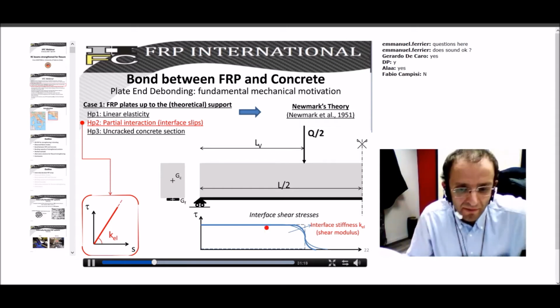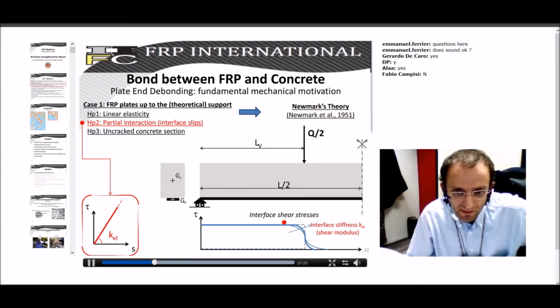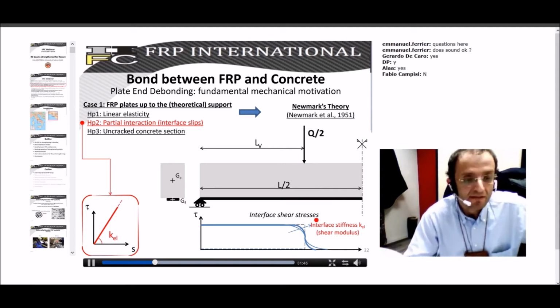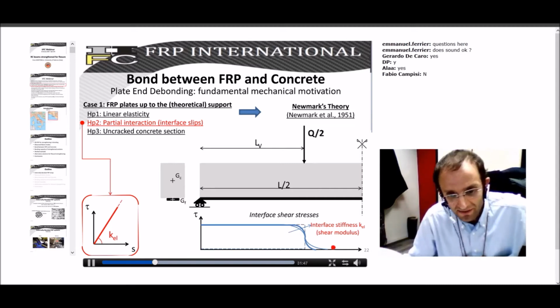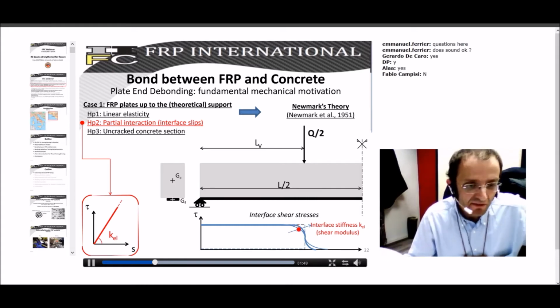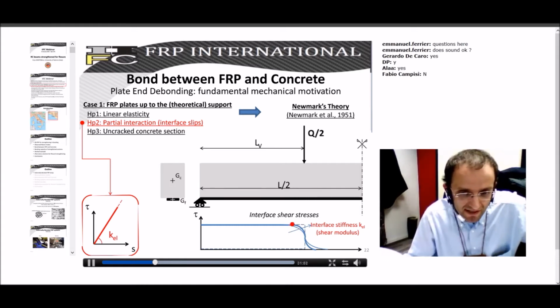But you can imagine that the solution you get by applying the Newmark theory in the case of partial interaction is very close to the Jourawski one, but it's not a stepwise solution. You have a gradual transition between non-zero tau up to the zero tau, and this transition is as gradual as the interface is flexible. So if you have a flexible interface, you have a more gradual transition. If you have a very stiff interface, your solution basically reduces to the former one.